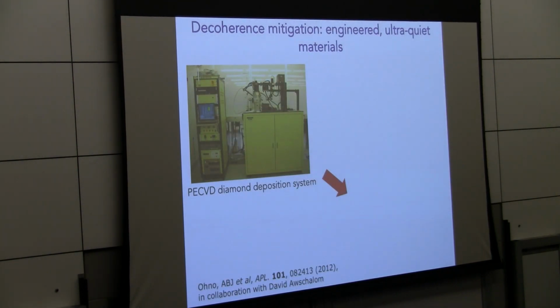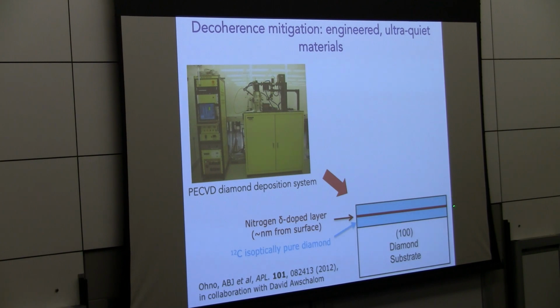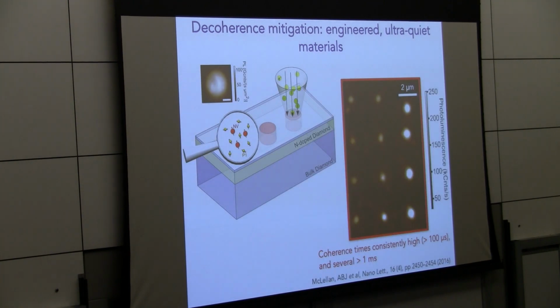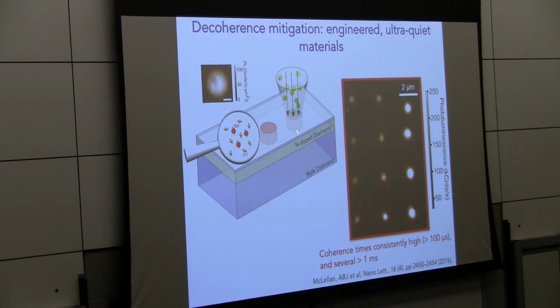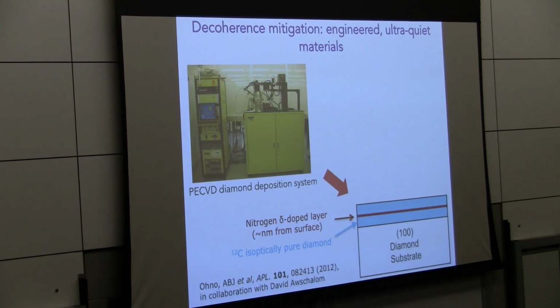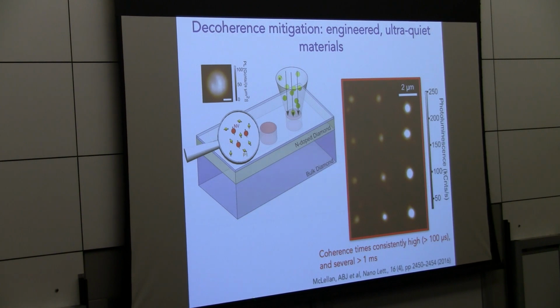Just a quick interlude to say that we're really interested in ultra clean materials. The surface is a bit harder to control, but we do start with very clean diamond by growing a diamond with a CVD process, and we engineer these NV centers to reside within nanometers of the surface using a delta doping technique. In a further effort to maintain the coherence of these NV centers as best as possible in terms of the bulk material, the doping from the CVD growth just introduces the nitrogen. One wants to introduce the vacancies as well in a very gentle process, and we do this with a transmission electron microscope, using the lowest energy electron irradiation of about 150 keV, which just barely frees up a carbon atom. And we can also do this in a spatially localized way. But the point is that using this combination of CVD growth and electron irradiation, we can get consistently high T2s in the bulk.